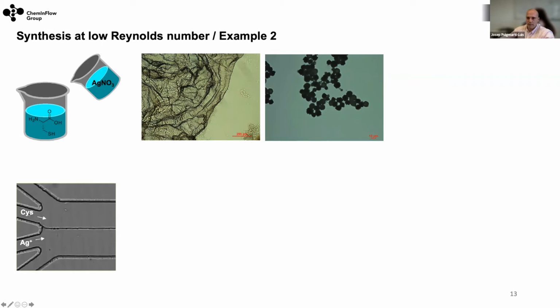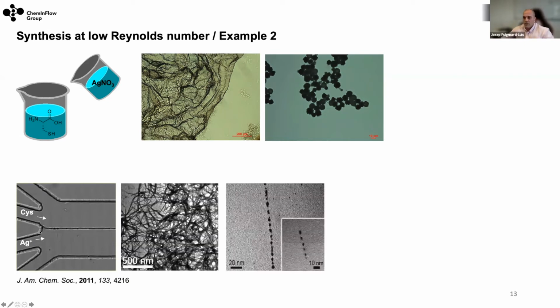And this is what we did. We have the 4-inlet device, with the cysteine and the silver. And what we observe is that now, because of these controlled reaction-diffusion conditions and the shear stress that this coordination polymer experiences when it is being generated, we can observe the generation of fibers. So instead of membranes, we observe the formation of fibers. We also observe the formation of silver sulfide. This is a semiconductor crystal that is generated just because of the morphology. You cannot generate this in the membrane, but when you have fibers and you focus the E-beam on those fibers, you can generate this semiconductor out of a biotemplated, functional material.